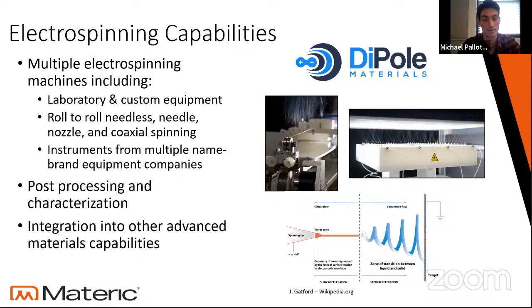Versus, to the right of that is the Inovenso PE550, which we have at our facilities, which is a needle and nozzle based system. From there, we can get a little bit more tunability on the nanofiber side. Although they're different in their nanofiber production mechanisms, they both follow the general rules of electrospinning, which is forcing a solution into a Taylor cone by applying an electric field and then capturing the nanofibers produced onto some sort of substrate or deposition section with an opposite charge relative to your charged surface, creating the Taylor cones.